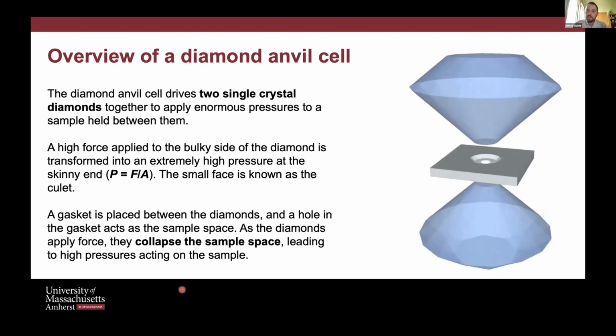So all diamond anvil cells, no matter what they look like, boil down to this simple picture of two diamond anvils that you're pushing together. We use a gasket material between the diamonds. We don't just squash the sample with two anvils. I think in the very early days, that's how the experiments were done. That doesn't lead to a uniform hydrostatic pressure around the sample. It leads to a very uniaxial pressure, which is not really what we want. You can't really do single crystal. You can imagine how a single crystal experiment would go if you just squashed it with two diamonds.